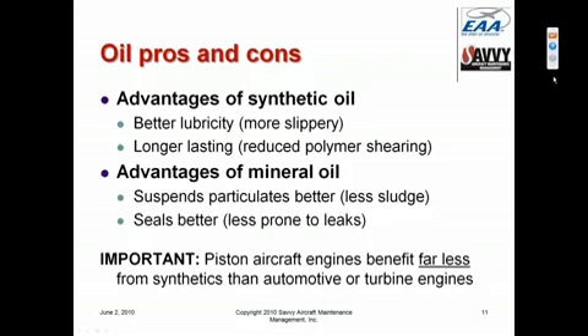So once again, the advantages of synthetic oil over mineral oil are that it's slipperier, has better lubricity, and that it can last longer because the phenomenon of polymer shearing, which degrades the viscosity of mineral oil over time, is very, very much reduced with synthetic oil because it doesn't have that branchy structure.